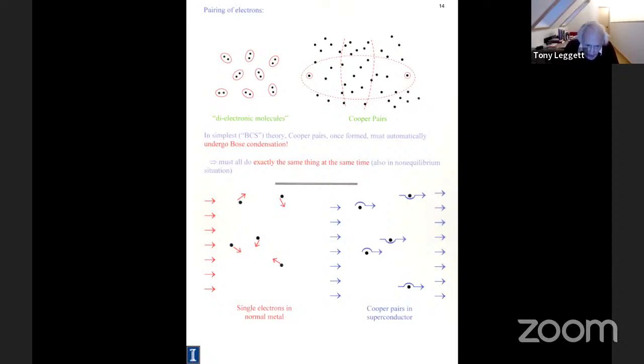And that's basically the analogy of what happens to the electrons in a normal metal like copper at room temperature. You give the electrons a kick, for example, by dropping the magnet, so causing an electric field around the tube. They will initially all move off together, but after a bit, one electron will run into an impurity, be scattered by it, and go off in a new direction. And after a short time, the electrons will all be running in random directions. There will be no current anymore. So in other words, the current will die away, typically in about a billionth of a second, very fast indeed. So the electrons in a normal metal are the analog of school kids in the forest.